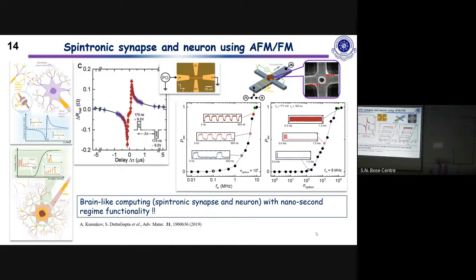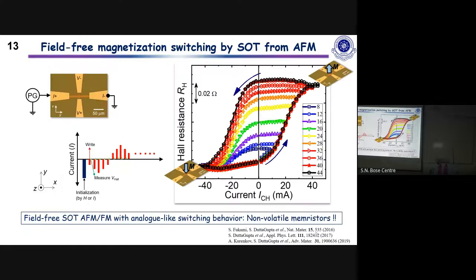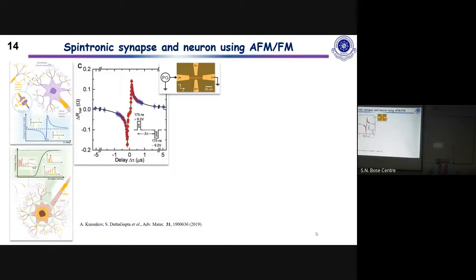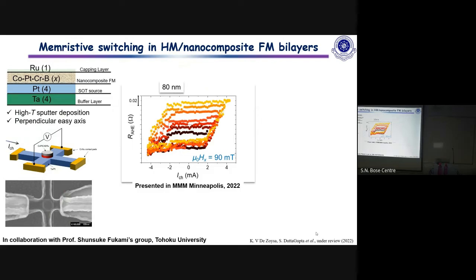The only problem is these devices consume power of around 70 to 80 nanojoules, while our brain operates at around femtojoules. So there is still a huge energy mismatch, but it still emulates the functionalities we have in our brain. More interestingly, when we were doing this work, we found that this memristive functionality is lost when we decrease the device size. There was a critical dimension of around 200 to 300 nanometers, below which this multi-level behavior didn't really show. So we were trying to see multi-level behavior at much reduced dimensions.